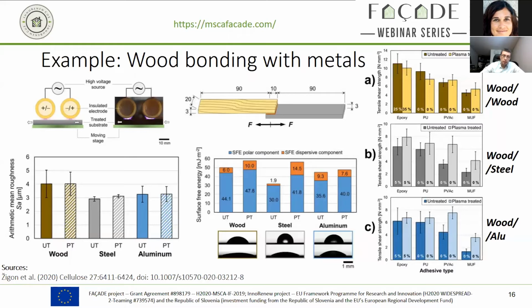One thing that is particularly interesting with plasma treatments is the combination of different materials classes. That's usually quite challenging. In this case, what was done is pre-treatment of different substrate materials, as seen on the top left side. Afterwards, adhesion strength tests of the formed lap joint were undertaken.